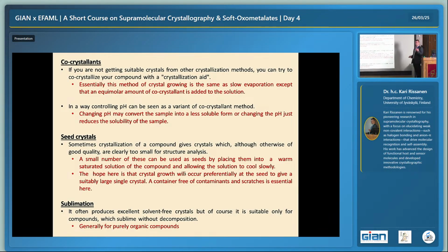This is a typical trick when you have a very complex amine, for example. You try to crystallize, and it's always an oil. You don't get it, it always comes as an oil. So the easy thing is to add, let's say, hydrochloric acid or hydrobromic acid to make a salt out of it. So you protonate the amine to make an ammonium cation, and then you have a salt.